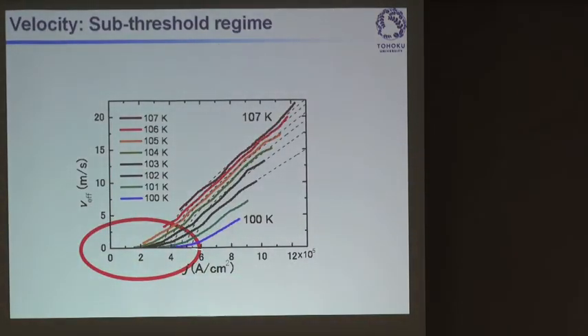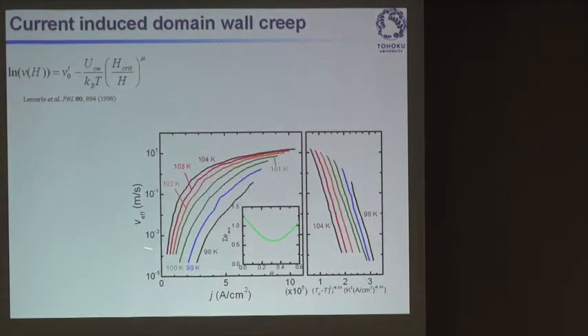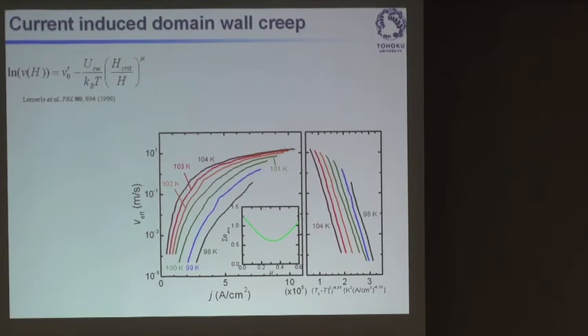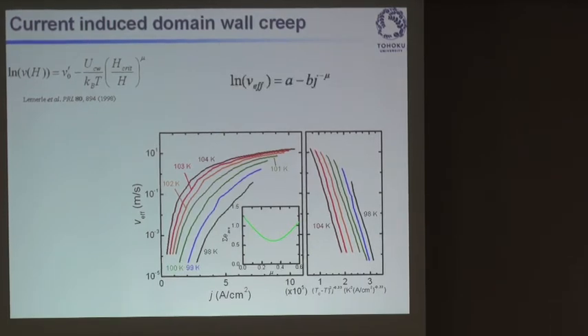When you do the measurement carefully around here, you see that the velocity is exponentially dependent on the current density because of this collective phenomenon. The same collective phenomenon has been observed in metallic structures using magnetic field. This group has shown that the velocity dependence on magnetic field can be written in this form, with a critical exponent here, which we indicate as mu. So we assume that although in their experiment they use magnetic field, we are using current to drive this creep motion, the gradual motion of a domain wall.